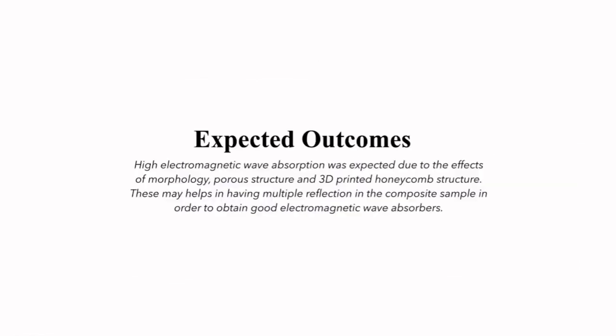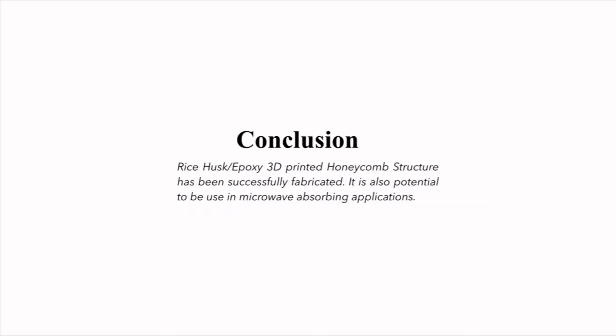as my reference. For the expected outcomes, high electromagnetic wave absorption was expected due to the effects of morphology, porous structure, and 3D printed honeycomb structure. This may help in having multiple reflection in the composite sample in order to obtain good electromagnetic wave absorbers. For the conclusion, the rice husk ash epoxy 3D printed honeycomb structure has been successfully fabricated. It is also potential to be used in microwave absorbing application.